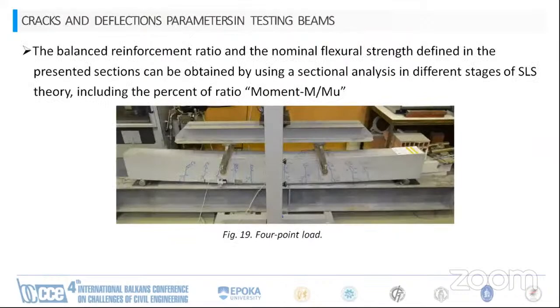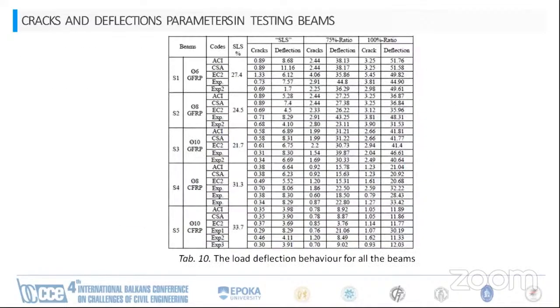The balanced reinforcement ratio and the nominal flexural strength defined in the presented sections can be obtained by using a sectional analysis in different stages of SLS theory, including the percentage of this ratio. In this table are presented the crack and deflection parameters in testing beams for SLS, 75% ratio and 100% ratio.